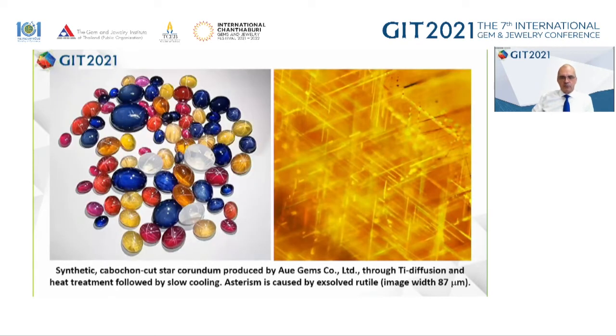This is now a rather recent development, and this is actually very high quality material. So Aue Gems, they produce star corundum now. So they take synthetic corundum and apply some titanium diffusion and heat treatment. And then upon slow cooling, titanium oxide, that is rutile needles, can exsolve and form this three-dimensional pattern that then causes a six-rayed star effect. And so this is now available in quite good quality and quantity. So the largest stones that you see here exceed 25 millimeters across.